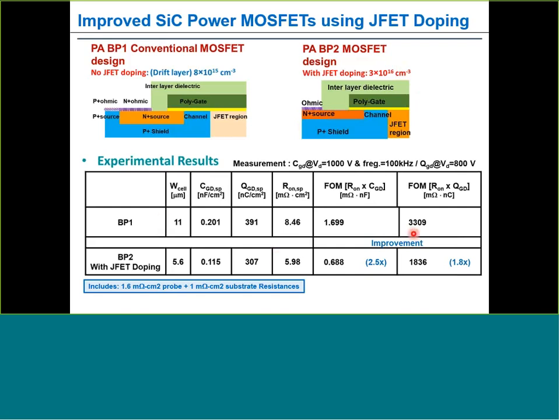So the upper part shows the results we obtained in BP1 with the conventional design. With that, we had an RDS-on of 8.46. This includes these parasitic resistances. And then we had a CGD of 0.2 and a QGD of 391. By using the new structure with the JFET doping and orthogonal contact, the RDS-on went down substantially, and so did CGD and QGD. So this results in a big improvement in the figure of merit, which I've defined in 2 ways. One is the product of R and C, and the other is the product of R and Q.